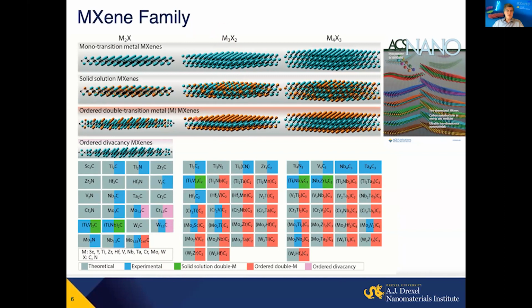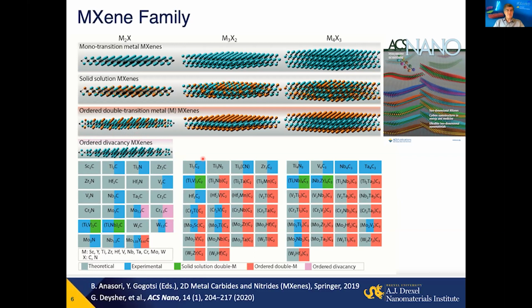We can make materials from one transition metal, for example, molybdenum on the surface, and another one, titanium, in the middle. These are known as out-of-plane ordered MXenes. Or it's possible to make MXene where there are alternating atomic columns of different elements, and if you etch away one of them, you end up with in-plane ordered divacancy MXenes here. And this is only the beginning. More than 30 of this type of structures have been